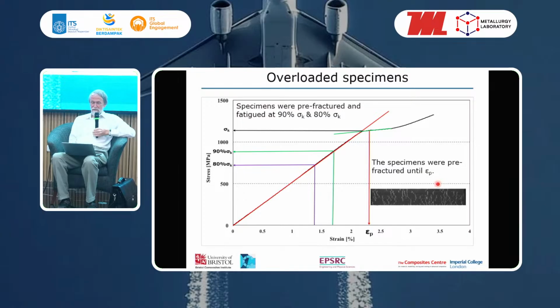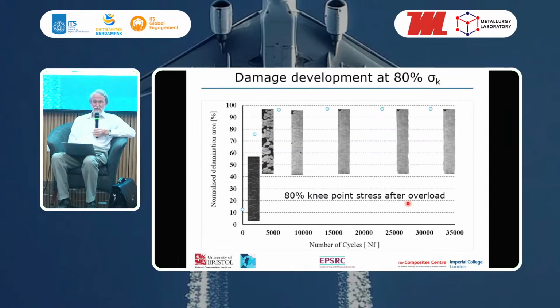So this is something which we can see in this slide here, that when it was fatigued at 80% of the knee point strain, after already exceeding that knee point strain in the first cycle, then you can see this is what it looks like at the start. And after 5,000 cycles, it's delaminated quite a lot. And we can see there's been a lot of the specimen now delaminated. And then after this point here, we've already got fully delaminated the material.